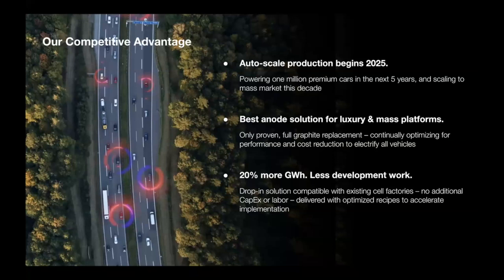We believe strongly that we've got the best anode solution for both luxury and mass platforms. We have a full graphite replacement that's more optimized around luxury or premium, and then we can use a lower blend percentage for more of the mass market as we focus on cost. The other thing that's important here, it's a drop-in replacement, as I mentioned. So overnight, you can take a factory and increase the output by 20%. So you can go 10 gigawatt hours to 12 gigawatt hours overnight without any change in your CapEx, using the same equipment, using the same labor. So it really is a huge step for an existing factory.